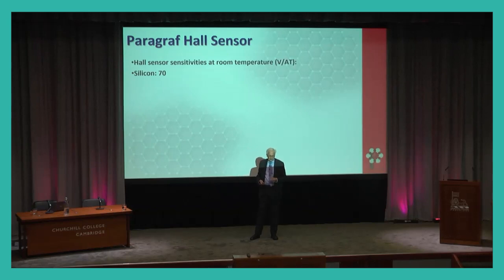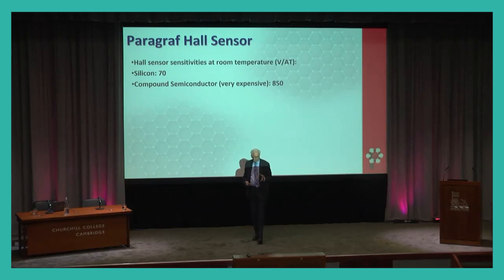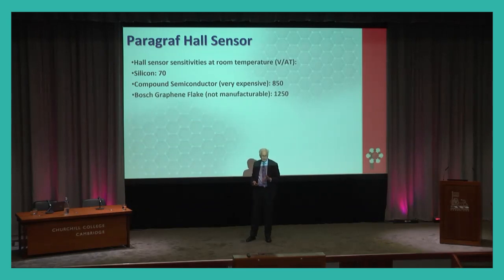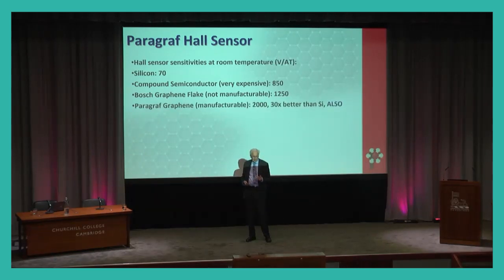Silicon has a sensitivity of 70. A compound semiconductor like gallium arsenide, a quantum well, has a sensitivity of 850 volts per amp Tesla. The Bosch flake, if you read their paper, was 1250 volts per amp Tesla. Our graphene Hall sensor is 2000 volts per amp Tesla, and it's manufacturable. So it's 30 times better than silicon, but also it can do things which silicon cannot do.